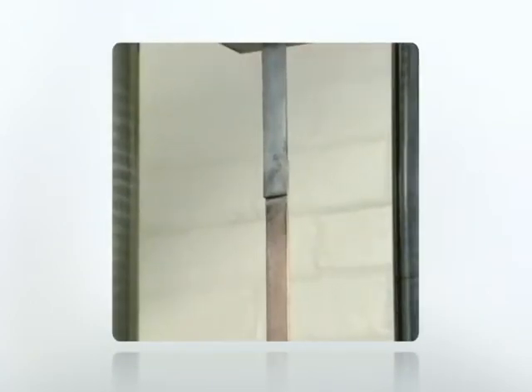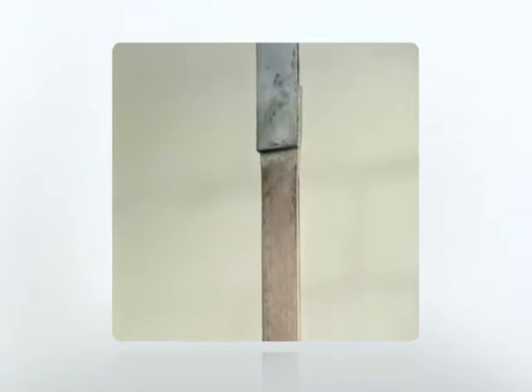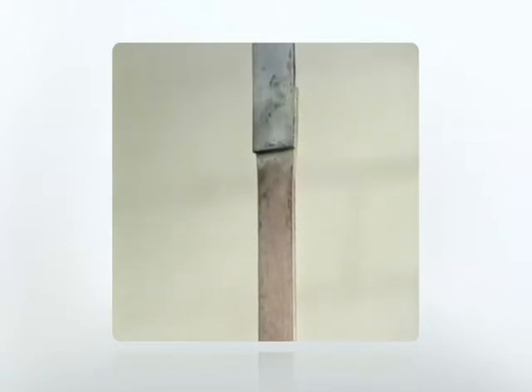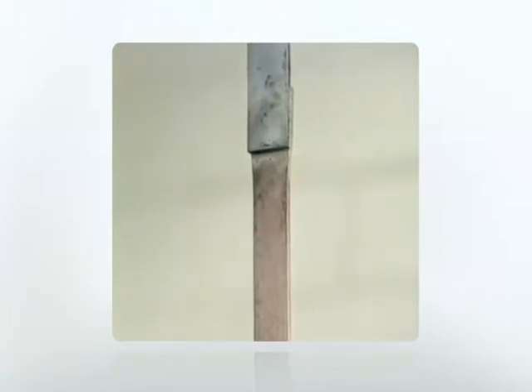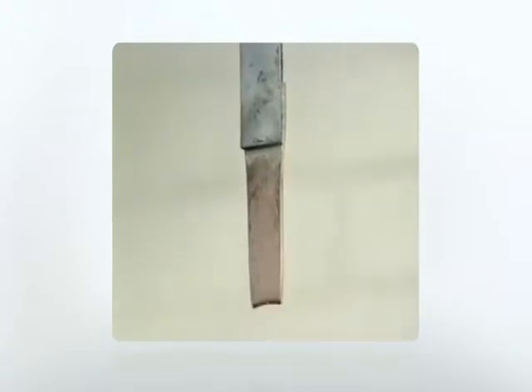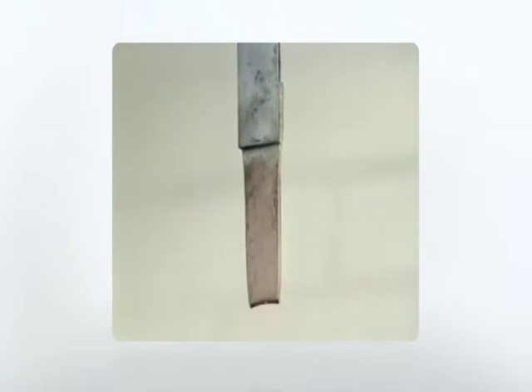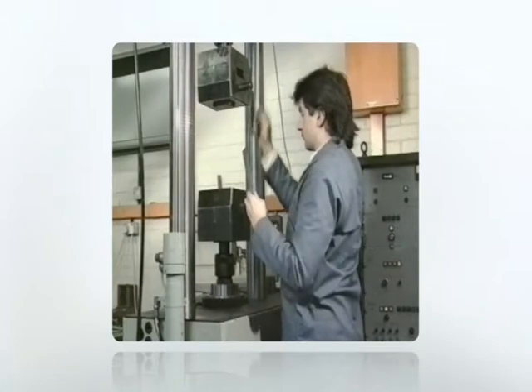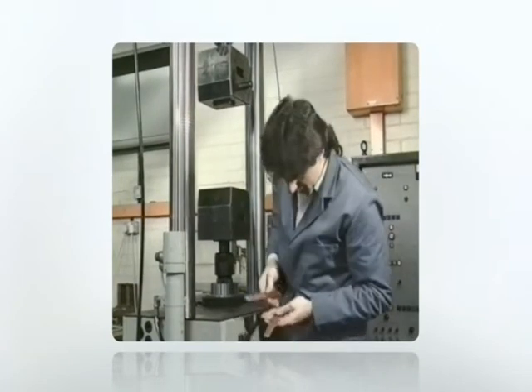In this instance, a copper to steel lapped joint is being tensile tested. A pulling force is applied to both ends of the assembly. As the load increases, the copper begins to stretch until it finally breaks, but the joint is still intact. This test clearly demonstrates that a properly made brazed joint can be stronger than the parent metals used in its construction.